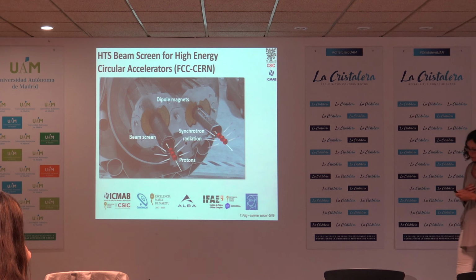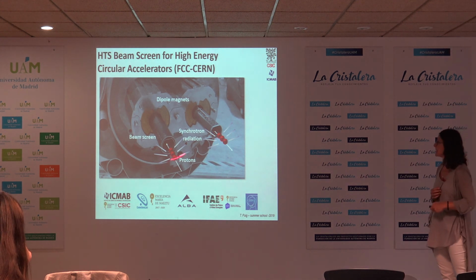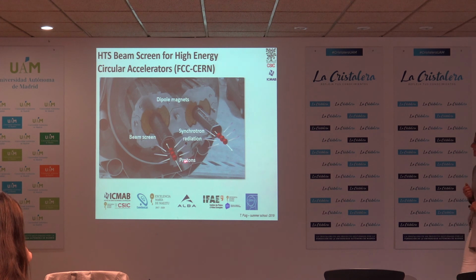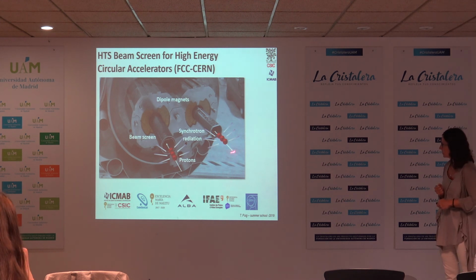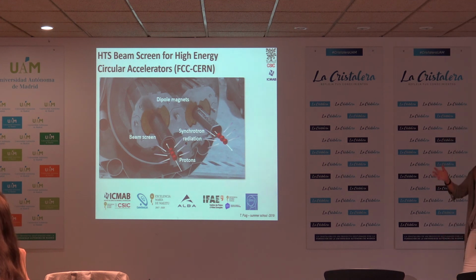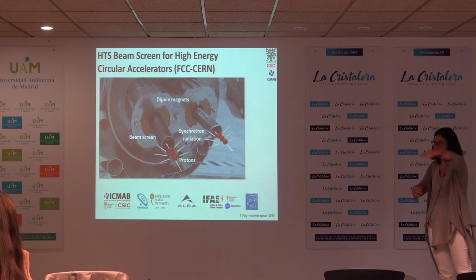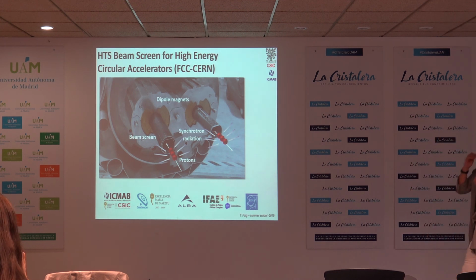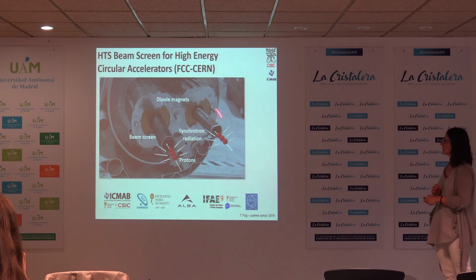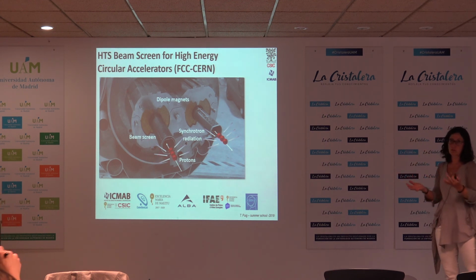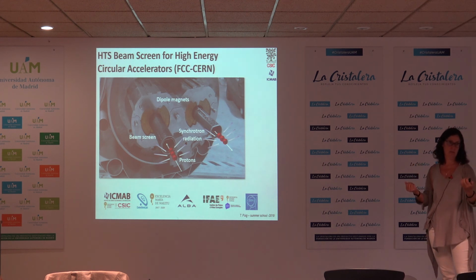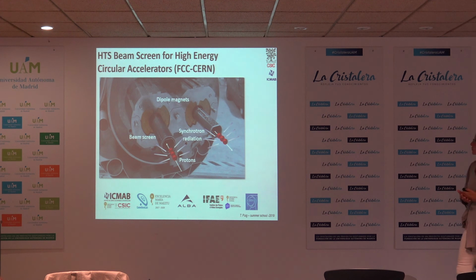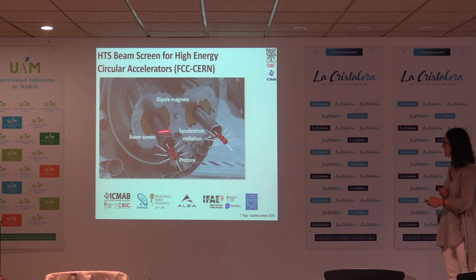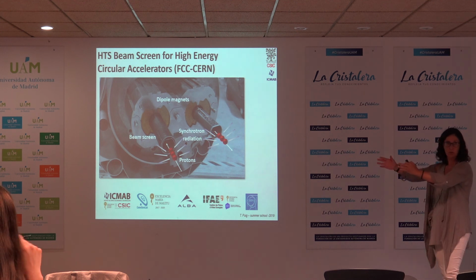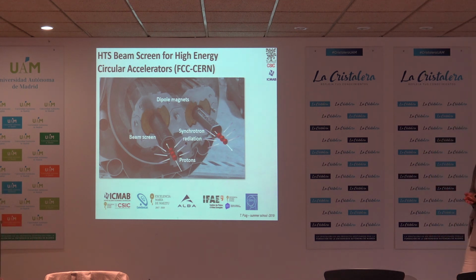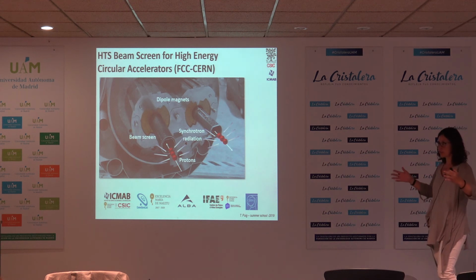But I just want to mention also that superconductivity in accelerators can also be in another place, and that is in the beam. When you have the proton beams which are circulating, there is a lot of synchrotron radiation being generated because you are circulating charged particles. And all this radiation is generated very close to the dipoles. So this synchrotron radiation is then damaging the dipoles and the magnets. And therefore, in order to screen this, they put in a beam screen. These are the tubes where the protons will circulate through, and these tubes are made of stainless steel to avoid this synchrotron radiation touching the magnets.